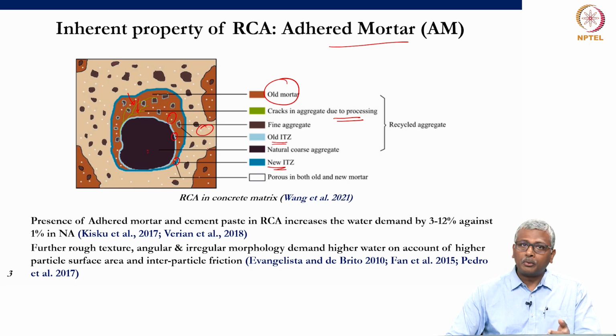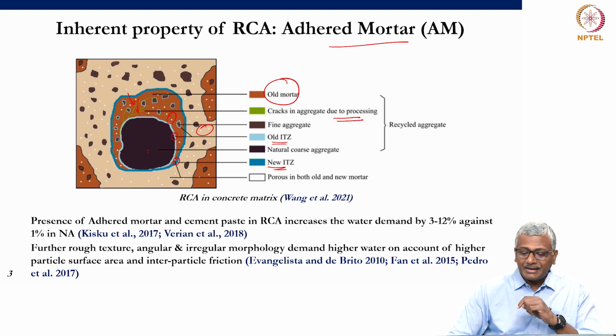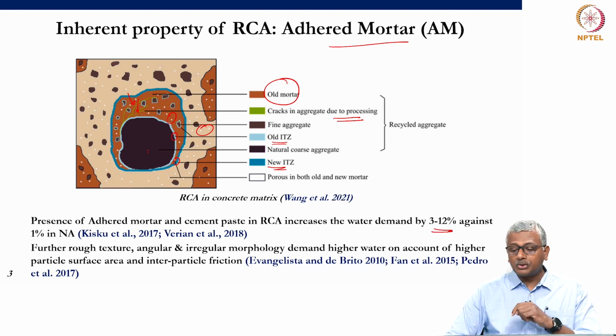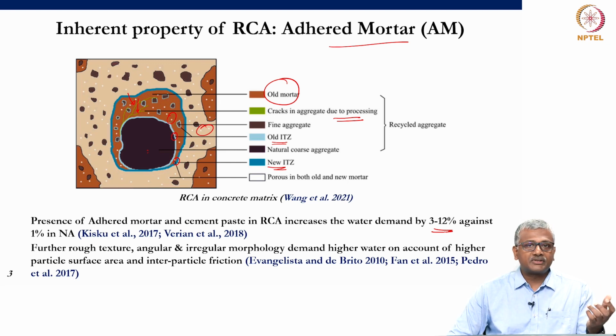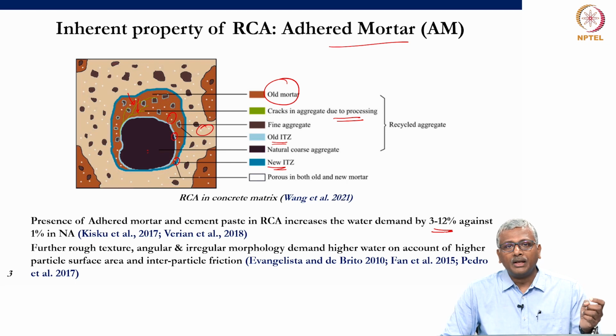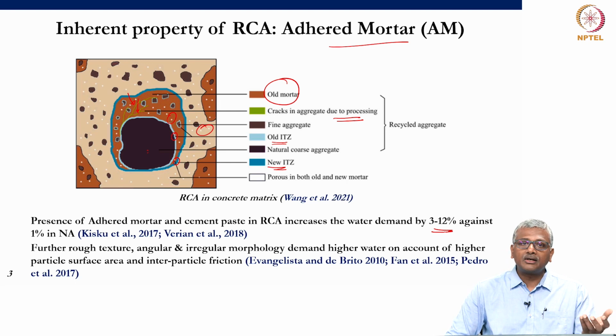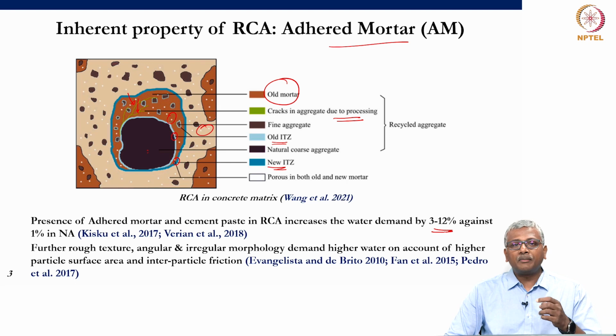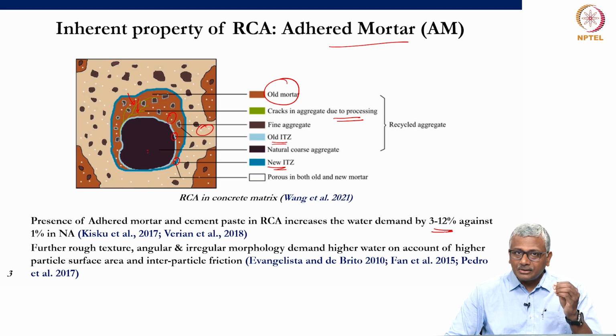So, it has been reported that the presence of adhered mortar and cement paste in your recycled concrete aggregate can increase the water demand by 3 to 12%. Your normal aggregate, which is either granitic or basaltic coarse aggregate I am talking about, will typically have a moisture absorption of less than 1%, right. But when you actually start using recycled concrete aggregate with the same parent raw material, you may end up having 3 to 12% additional moisture absorption. So, that is going to be the critical component when designing your mixture for achieving workability and strength.